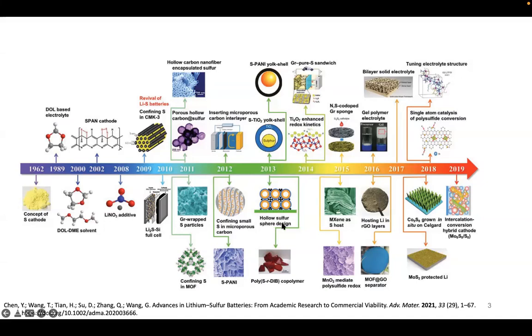A lot of hollow structures, sphere design. Inverse vulcanization was really popular 7 years ago, where basically you arrest the polysulfide shuttling by cross polymerization with this DIB, this diisopropenyl benzene polymer, and it's called inverse vulcanization because vulcanization is, of course, where you try to make sulfur bridges to then cross-link rubber, to make rubber, basically, by creating sulfur linkages.